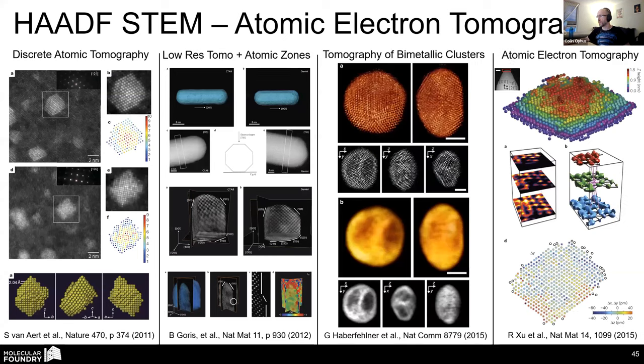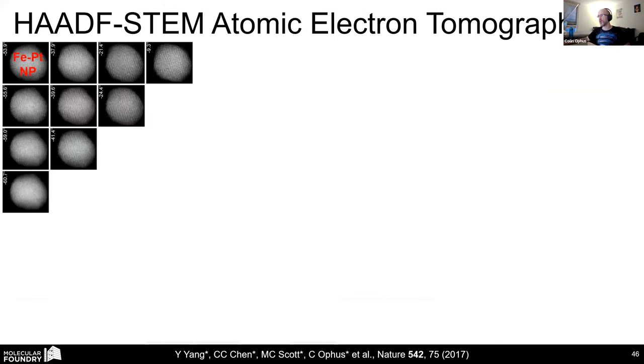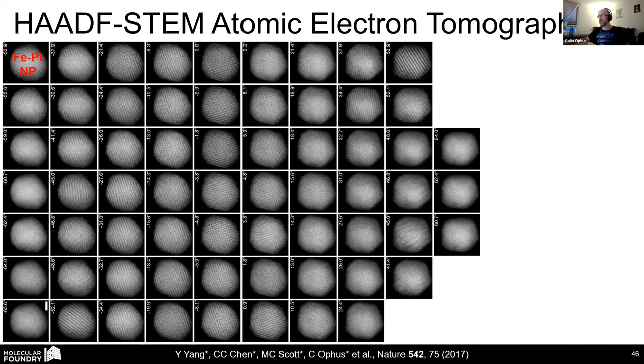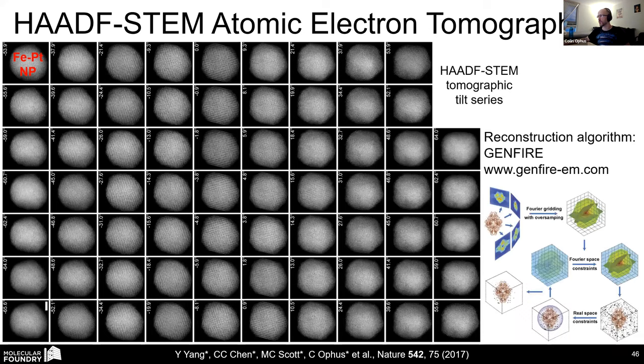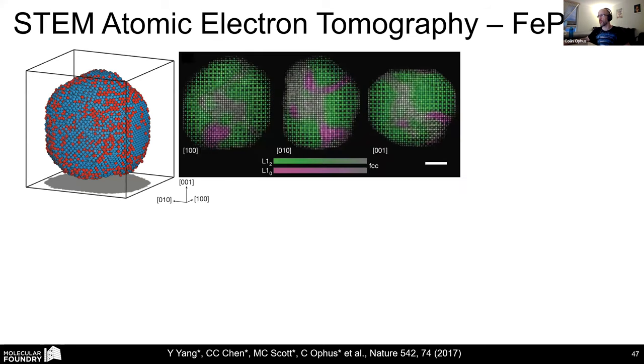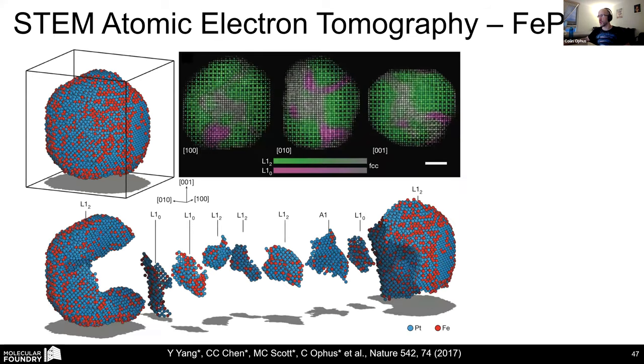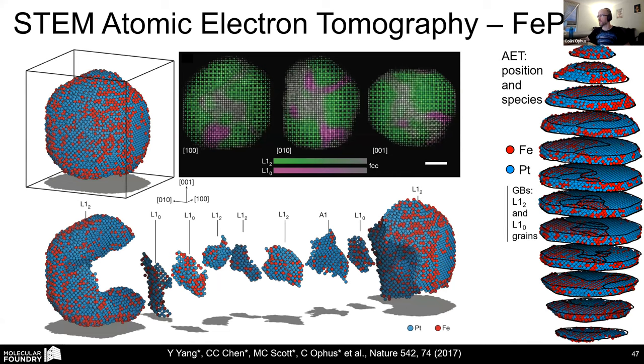Okay, so I will show you one more quick experimental example, but this is tomography of atomic resolution materials. We are able to solve the position of every single atom in 3D by doing these atomic electron tomography experiments. Traditionally, they're quite high dose. We record many, many images at different projections and then use computer algorithms to reconstruct the structure in 3D. Then we trace out all the atomic coordinates.